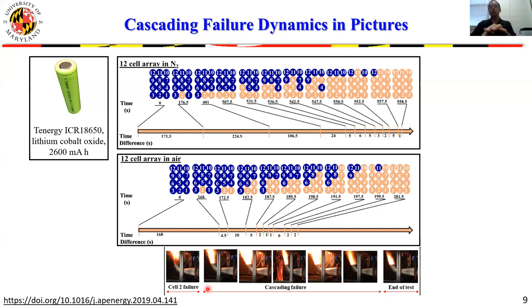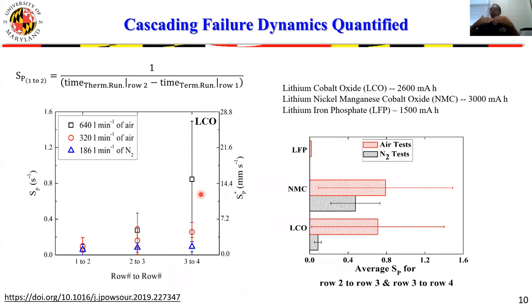Now, individual tests that were conducted were not 100% reproducible. In other words, when we failed cell two, that was the trigger cell, the cells did not fail in exactly the same sequence, but we did notice that the transport of thermal runaway from row to row was reasonably reproducible. So we quantified the rate of this propagation by calculating the rate or speed of transport by taking the average thermal runaway time in one row and subtracting the other and taking the reciprocal of this value. So if you take 1/SP, you get the timing it takes to jump from row to row.